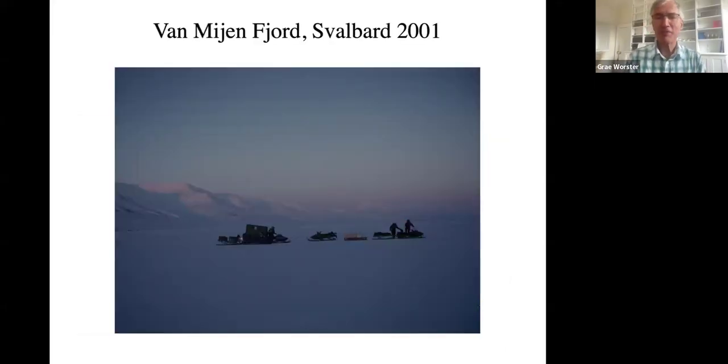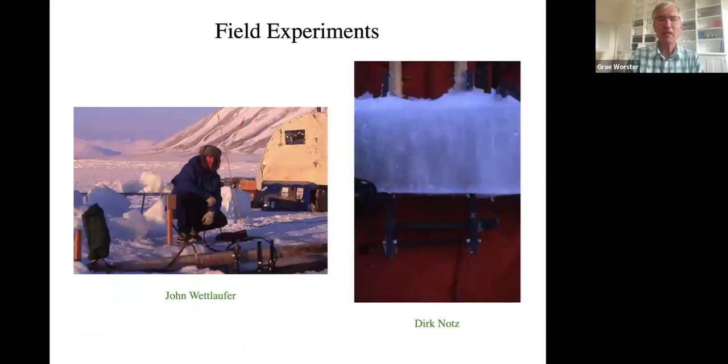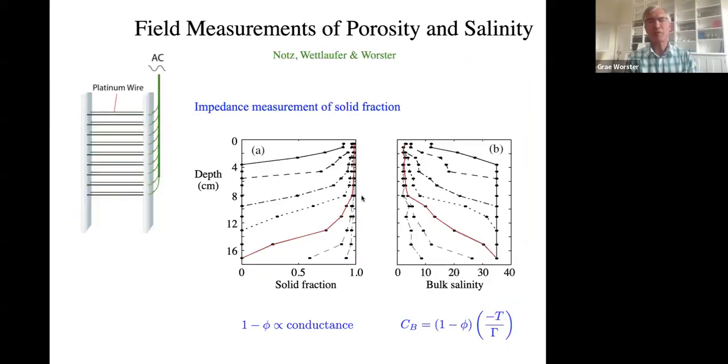So we went off to measure this stuff in the Arctic. Here's a picture of my colleagues. We now really are high up in the Arctic, on a place called Svalbard. Here's one of my closest colleagues, John Wettlaufer. These are instruments, and a PhD student who is anonymous, Dirk Notz, with his face out of the picture, holding a lump of sea ice with our instrument embedded in it. What that instrument was able to do, by measuring the conductance, was to measure the solid fraction, the fraction of the sea ice that is pure ice rather than brine.